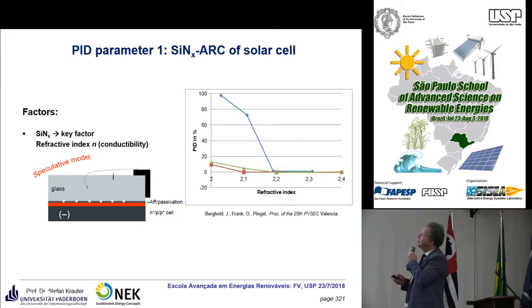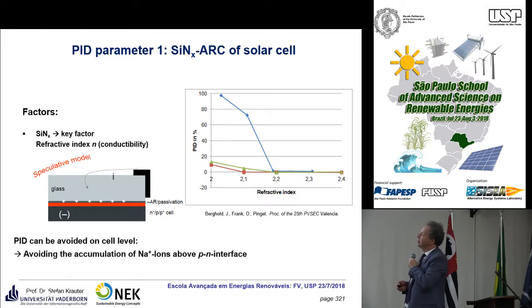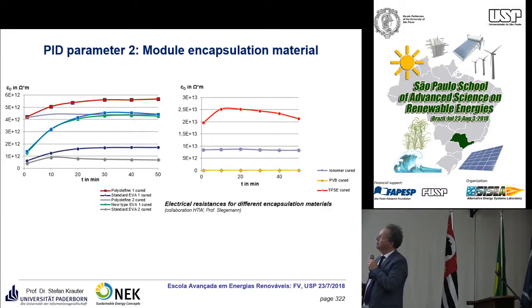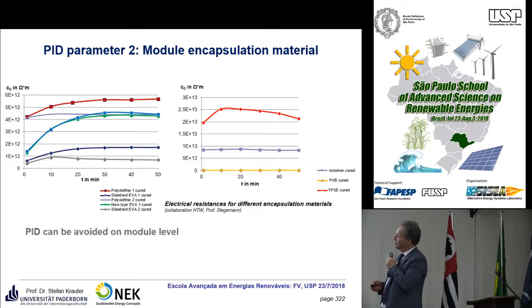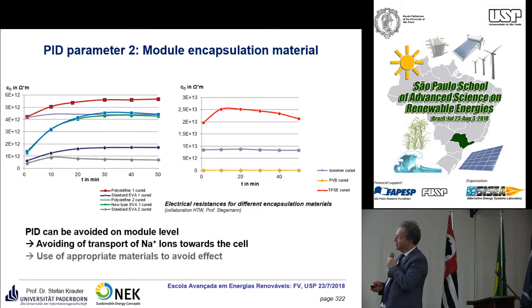You see there are a lot of PID. If you have a low refractive index, you go to high refractive index, there is no PID effect anymore. So avoiding the accumulation of sodium ions above the p-n interface. So you can block it via polyolefin, depending on the plastic you are using, or by conventional EVA, to increase electrical resistance. So just avoid the transport of natrium ion.